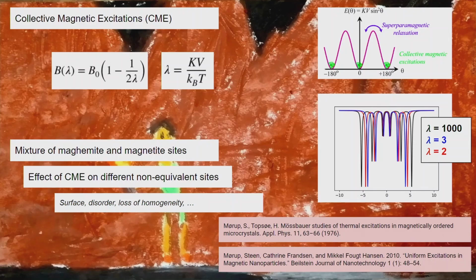But maybe the thermal energy lets the magnetic moment, the superparamagnetic moment, oscillate inside the well, so you will have a reduction in the mean magnetic field that is higher as the particle is smaller. The smaller the particle, the higher the reduction. This is an approximation that Mørup gives, valid for high volume, sorry, and low temperature.